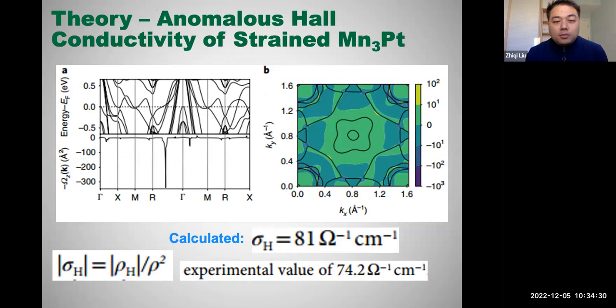Indeed, for this kind of metals, because they are not strongly correlated materials like the oxides, we could get very nice theoretical calculations. For example, Prof. McDonald's group did a calculation for us. They found that for the strained manganese platinum films, the anomalous Hall conductivity is 81, and experimentally we obtained 74. So that actually was quite close.